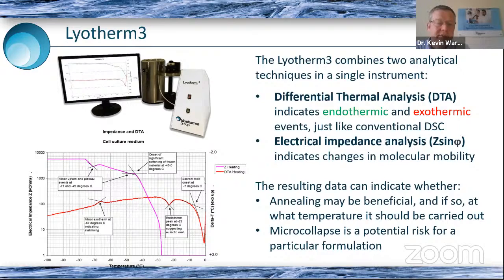When we looked at it under the freeze-drying microscope, we found that the cell culture medium here collapsed around -43. So whatever the impedance is telling us here in terms of the change in mobility, in this case can be directly related to the collapse of the product.